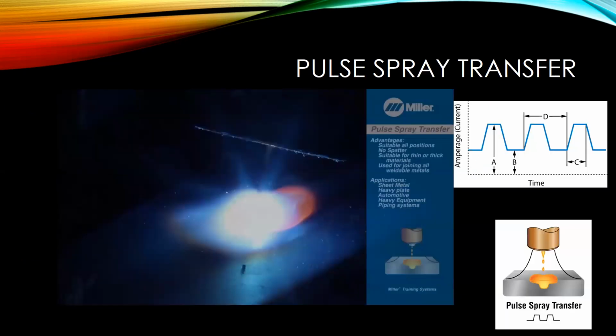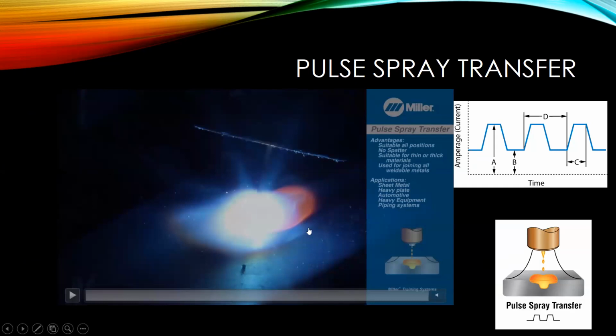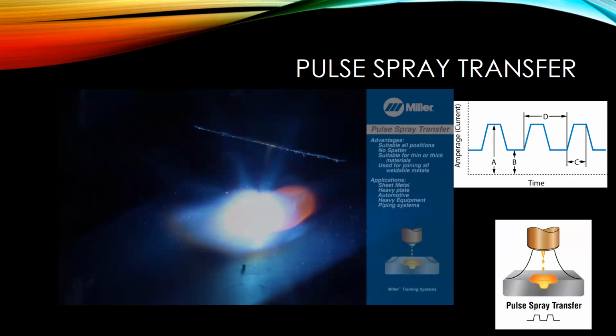So pulse spray transfer, now instead of just doing a constant stream of droplets across that arc, you're going to see that in slow motion, as the current rises, once we hit this peak, that'll allow us to transfer a droplet, and then we'll move to our background amperage, and that'll keep our arc maintained. So basically, we're going in between a high current and a low current or amperage, and that helps us